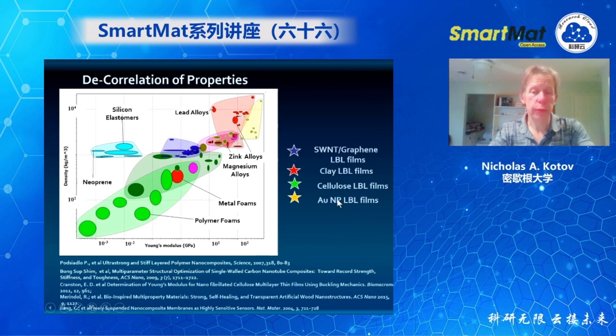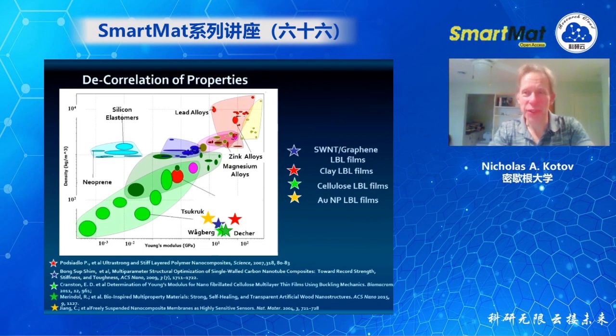So there are many types of nanometer scale materials which can be organized in nacre-like structures in these layered composites. And in all the cases, inevitably and surprisingly, or not, they reveal a very unique combination of the density and Young's modulus. And that's actually, looking back, not surprising because the contribution of interfaces and the mechanisms that are operational in nacre and in these materials are exactly the same. So, in fact, we can not only obtain the combinations which are in nacre, but much better.